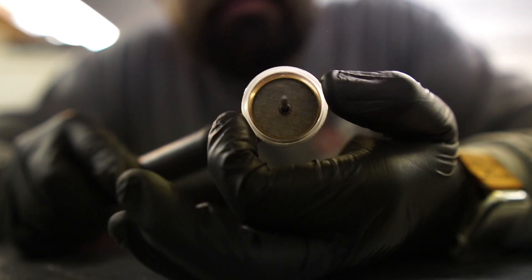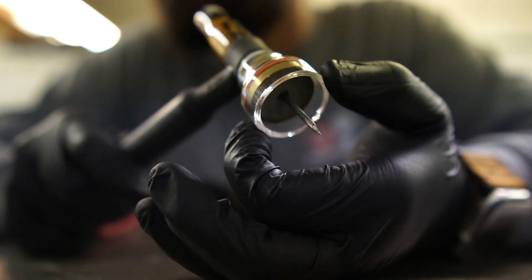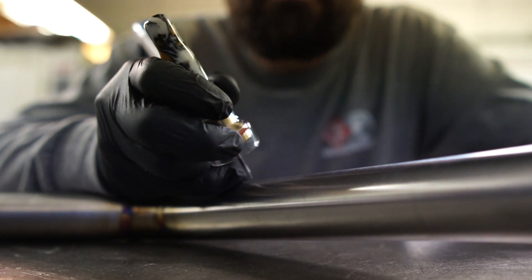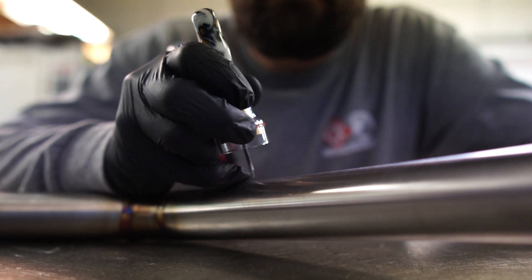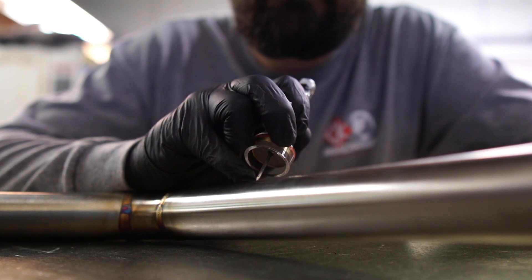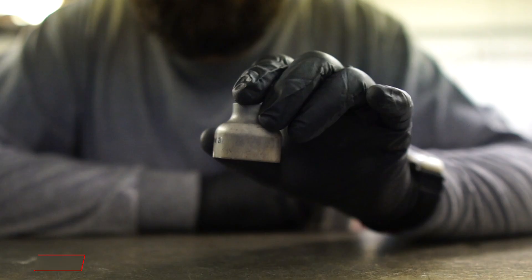The three inch diameter tube is large enough in diameter to allow us to use the number 17 cup to travel quite far before our weld oxidizes behind the cup. The smaller in diameter the tube, the smaller the cup can be due to the fact you're welding around a smaller radius and that will typically result in more stops and starts. Not as much coverage needed with shorter runs. Every cup size has its purpose, but a lot of it has to do with personal preference.